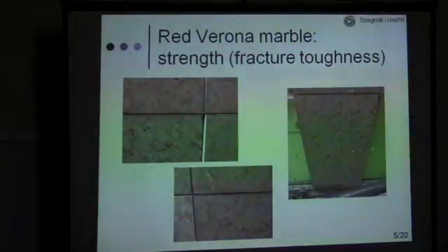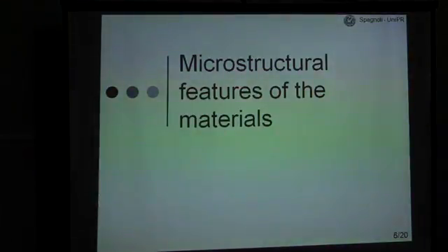In the case of the Verona marble, instead, one of the most frequent problems is related to the strength of the material itself, and there are experiences of cracking and some surface detachment of the material, and so this is a problem mostly related to the strength and more specifically to the fracture toughness of the material. So for these two kinds of marbles, we wanted to perform some investigation, starting from some microstructural features, and then mainly on the mechanical testing.